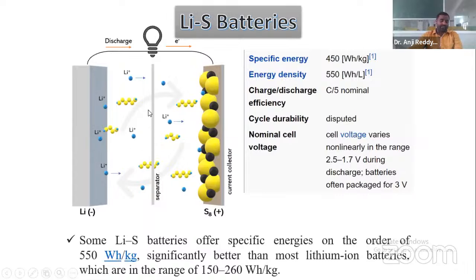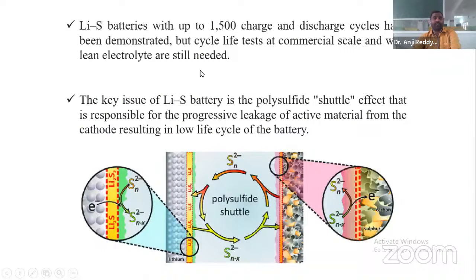For the electrolyte, for example, you can take a polymer electrolyte. But the cathode material has sulfur. Even the electrolyte may need sulfur. That's why we call it a lithium sulfur battery, particularly because the cathode materials have sulfur. These lithium sulfur batteries will give up to 1500 charge discharge cycles. Up to 1500 charge discharge cycles have been demonstrated. But cycle life tests at commercial scale and with lean electrolyte are still needed.